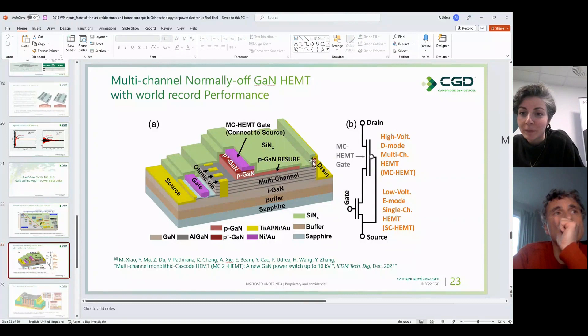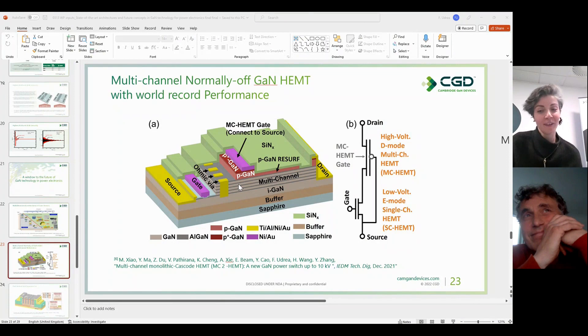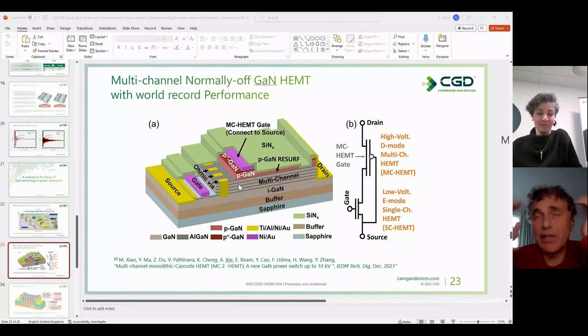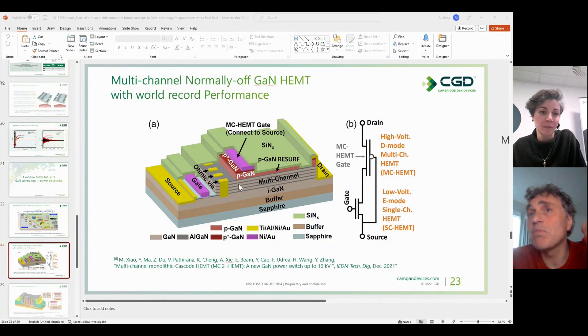From Jenny Feng, asking about process/manufacturing (PMT) variations of key parameters: we do have process variation in GaN, but our devices are fabricated at TSMC and the process variations are very well controlled there. Looking at the threshold voltage variation — a major problem in silicon carbide where it can vary by even one volt among reputable suppliers — our ICeGaN devices show very small variation, between 2.7V and 2.93V, which is significantly better controlled than SiC competitors.